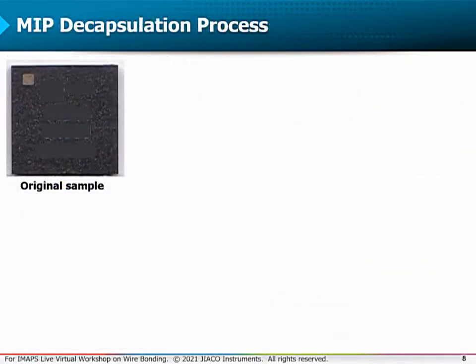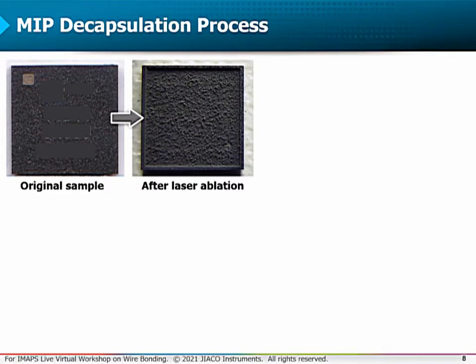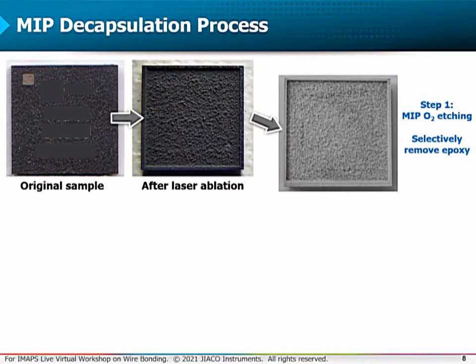So this is how the MIP decapsulation process looks. The starting point is the sample preparation, which can be laser ablation or mechanical polishing. Next, a high density oxygen plasma is scanned across the device surface, and by this the epoxy in the mold compound is selectively removed. After oxygen MIP etching, silica filler particles in the compound are left on the surface, and they can be seen as this white agglomerate layer.